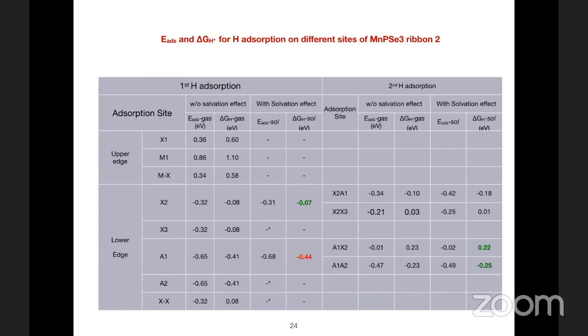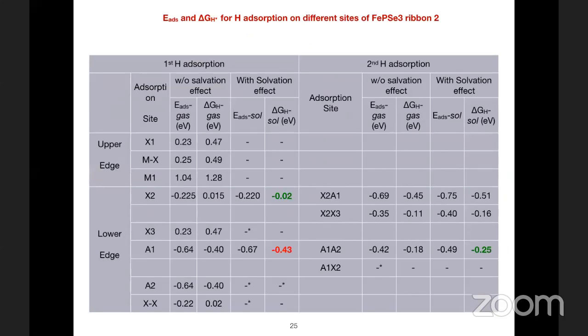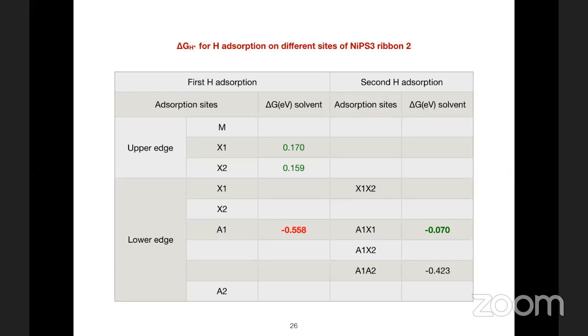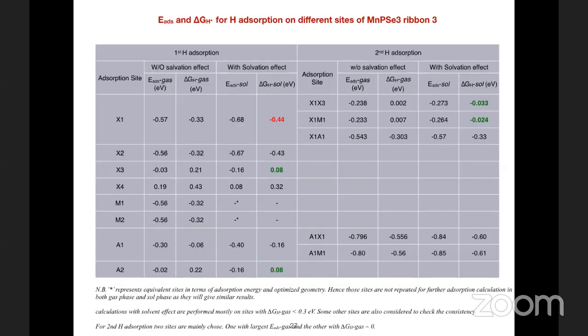And again, you see there are promising sites where the reaction can go ahead. This is for nanoribbon 2. You get a similar picture. There are X1 and X2 sites which are promising when the concentration is low, but at high concentration, the A1 site would get occupied by a hydrogen, but then in presence of that, you have the X1 site which could act as a catalytically active site. And that is sort of the story everywhere.